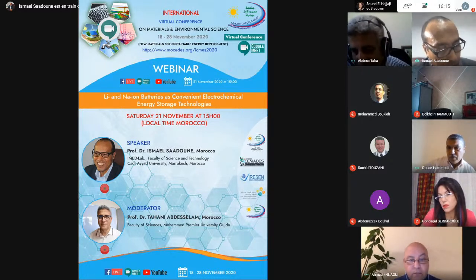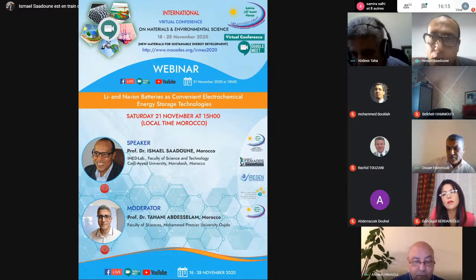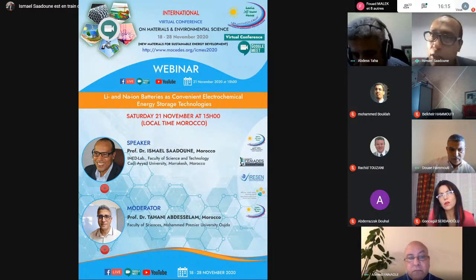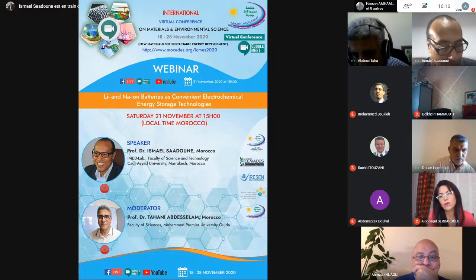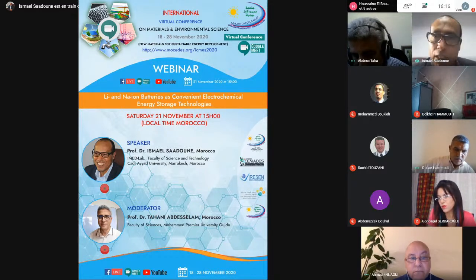Now you have an anode material, electrolyte, and cathode. This is the cell. So you should have fast lithium diffusion in the anode, fast in the interface between anode and electrolyte, fast also and safe inside the electrolyte, and between the electrolyte and the cathode interface. So now people are trying to prepare some solid electrolyte, polymer or solid like garnet or phosphate. But the problem is the interface between the solids. This is the big challenge: we have to prepare some interface to make easier the transfer from one side to the other side of the component of the cell. This is the big challenge.